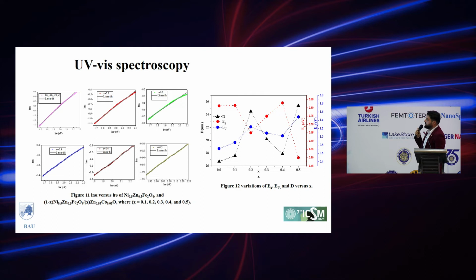There is an inverse relationship between the band gap energy and the other two variables, suggesting that the variation of our band gap energy is due to the quantum size confinement effect due to the variation of the size, and also due to distortion in the band structure due to the variation of the Urbach energy.